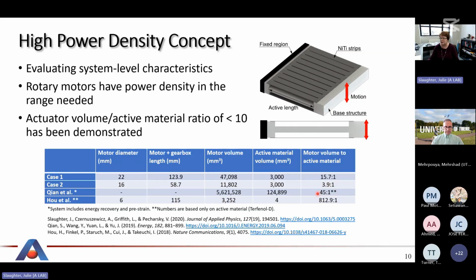Looking at some of the other systems, one was a heat-driven system, the other used Terfenol-D, a magnetostrictive. So you can see that we're actually in really good shape. There's other systems out there that are probably much better. This was a fairly old result, so I'm sure everything has improved by this time. But that's really where we're aiming, to get to that same type of ratio for the material volume to the active material volume.